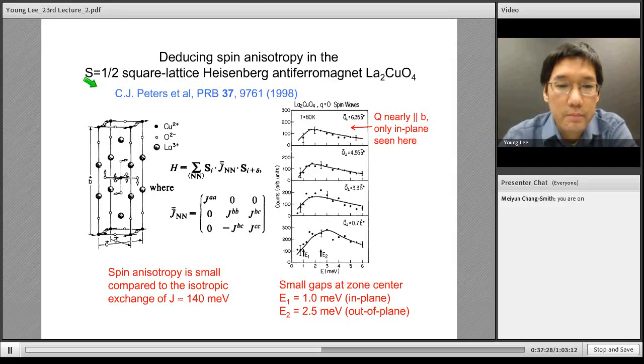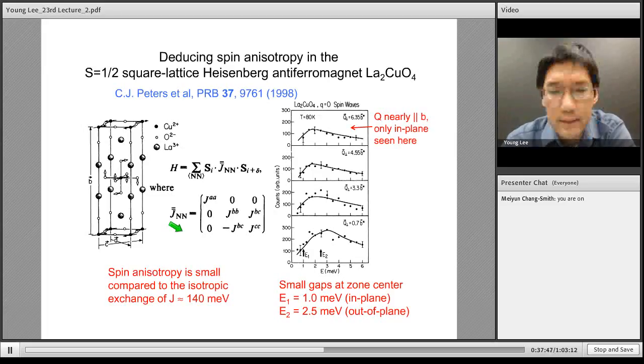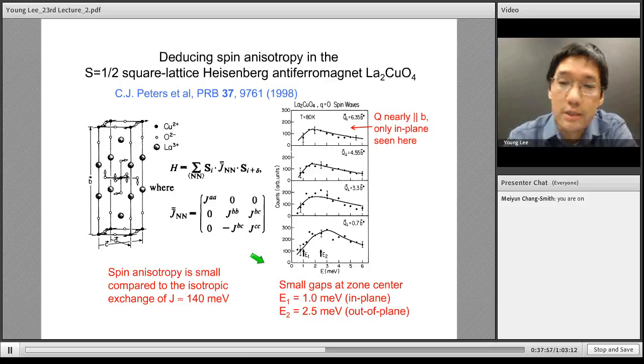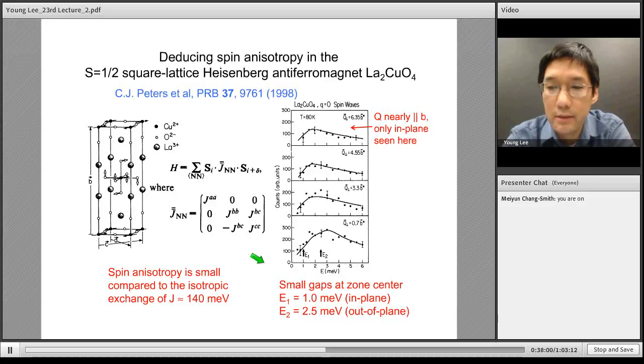This early paper by Peters et al., also done at Brookhaven, deduced two gaps. One of the gaps they attribute to antisymmetric exchange, and I'll say a little bit more about that in the coming slides, also known as a Dzyaloshinskii-Moriya interaction. Another gap is related to there being some exchange anisotropy, like an XY-like tendency for the spins.